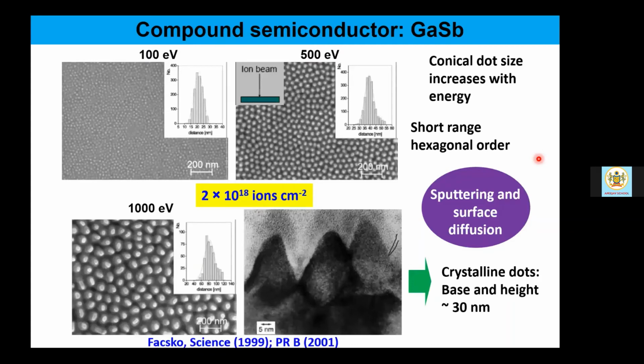Now this is actually a paper in Science in 1999, which gave a huge boom to this field. This German group bombarded a gallium antimonide target with argon ions, using different ion energies. We get to see that for a similar ion fluence of 2 into 10 to the power 18 ions per square centimeter, we can vary the dimension of these dots that are formed. Short range hexagonal ordering is observed, and conical dot size increases with ion energy.